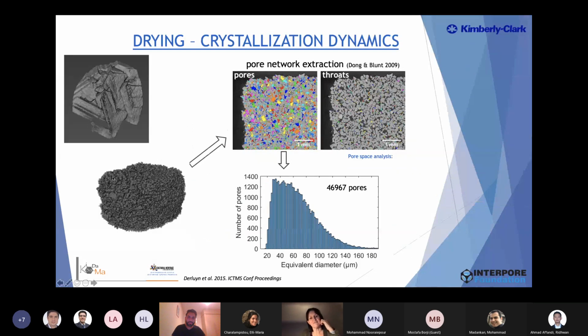If you have a CT scan, you can also extract the individual pores using pore network extraction, for instance using the procedure already published in 2009 by Hu Dong and Martin Blunt. You are able to extract those.